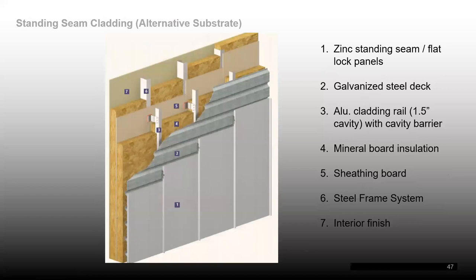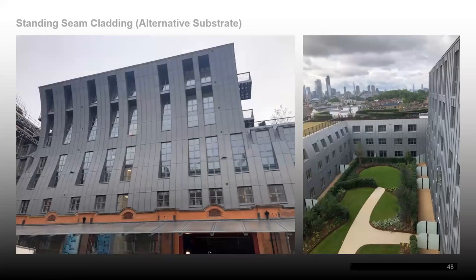Here we can see an alternate substrate that was used. Galvanized steel can replace the plywood by using non-combustible, limited combustibility insulation. Islington Square in London was constructed using a galvanized deck and 0.8 millimeter thick zinc.